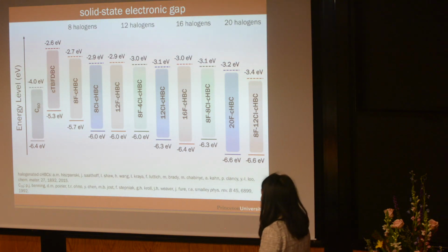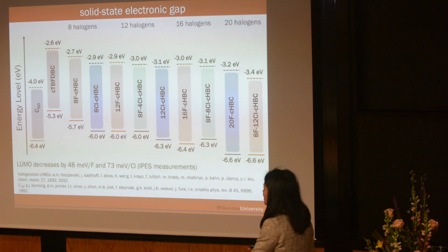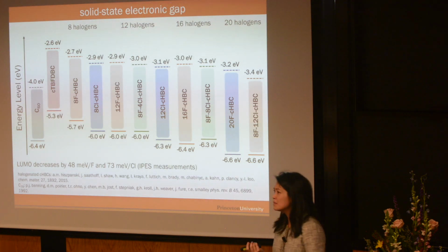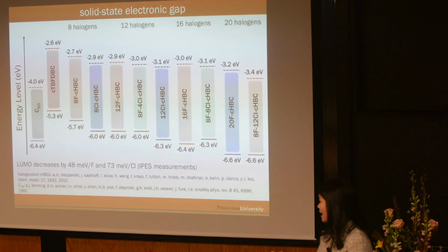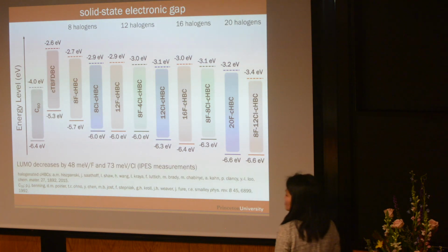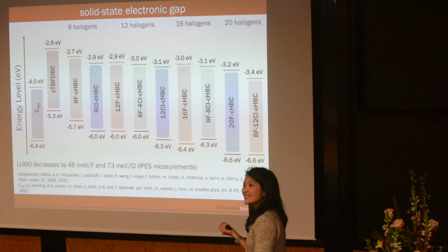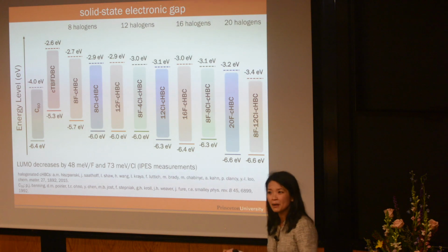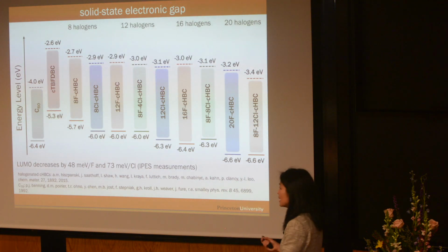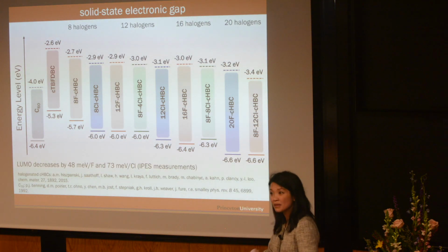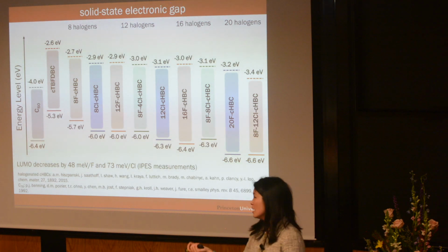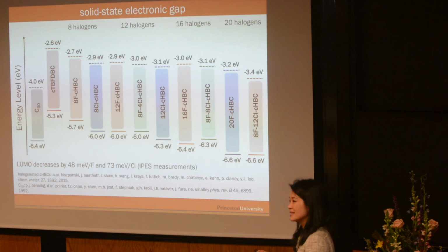Makes sense? What was nice was you can actually quantify this, and the LUMO actually decreases by about 50 millielectron volts per fluorine you add, and by about 73 millielectron volts per chlorine you add. This is nice because now we have a design rule. If we wanted to make next generation materials, we can come back and use this as a rule of thumb to get us to where we need to get to without having to make the compounds and then quantify it, right?